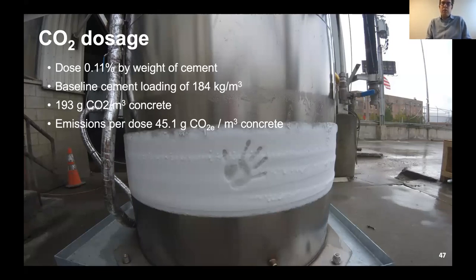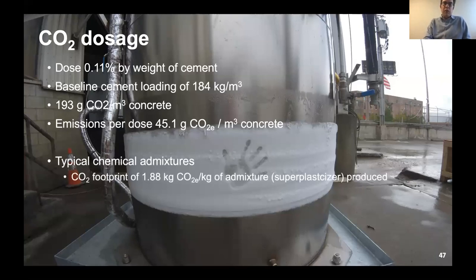the amount of cement in the mix. The Portland cement portion of the binder is 184 kilograms per meter cubed in this particular case study. So if you take that dosage rate by that cement loading, you'll come up with 193 grams of CO2 per cubic meter of concrete. And so if you looked at that amount of CO2, we're emitting about 45 grams of CO2 to do that. But if you look at typical chemical admixtures, and you look at their EPDs, you have about 1.8 kilograms of CO2 emitted per kilogram of admixture produced.